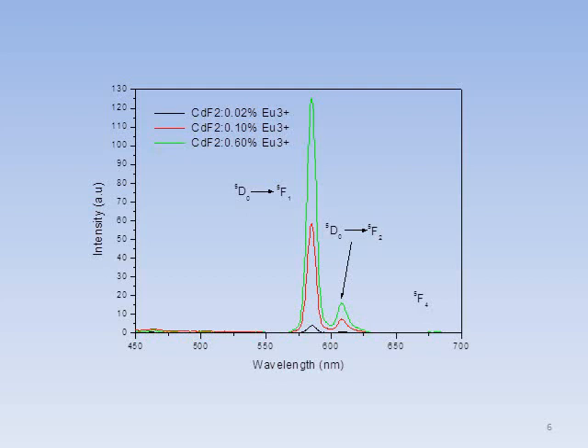On the contrary, the 5D0 to 7F2 electric dipole transition occurring in the red region is very sensitive to the local environment and its intensity depends on the symmetry of the crystal field around the europium ion. In accordance with other publications, it is established that the relation between these two transitions is influenced by the symmetry of the host lattice.